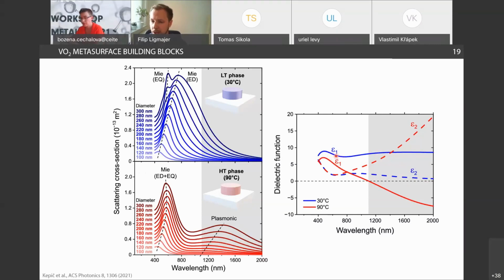Of course, there is some change in the refractive index. There is virtually no change in loss, which is the imaginary part of the dielectric function. And this is exactly what we are using here in our work. So here in the metallic, so to say, state, which is kind of a misnomer in this context, because as you see, VO2 no longer behaves like a metal at these wavelengths. You observe mere resonances, that is dielectric resonances of bound electrons and their currents in the nanodisk, which we ascribe to an electric dipole and electric quadrupole mixture.